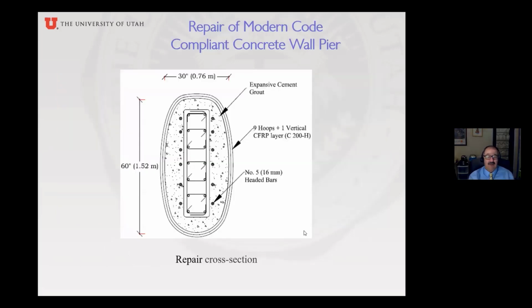So this is what it looks like in cross section. This is the original 1 by 4 feet wall. And you see we ended up with a 30-inch by 60-inch tub here. We have 9 hoop layers of carbon fiber. And we found in previous tests that we did, actually again under the Mountain Plains Consortium, if you put a vertical sheet, that helps you consolidate the stresses that this carbon fiber is going to see, because sometimes you have a little bit of a vertical action. So it's good to put at least 1 vertical layer on the outside. And here you can see number 5 headed steel bars. There's 5 on this side, actually 6 on this side and 6 on that side. The area of this kind of is equal to the area of the original steel inside.